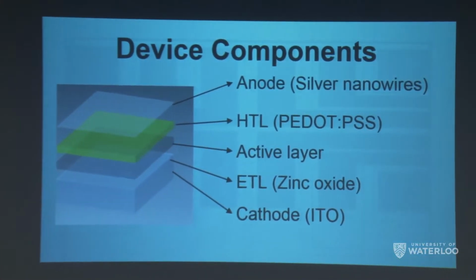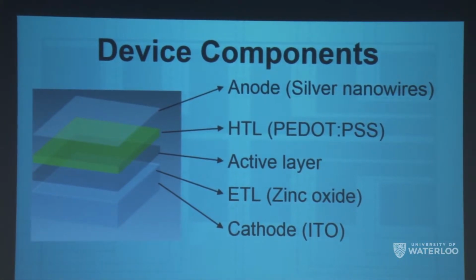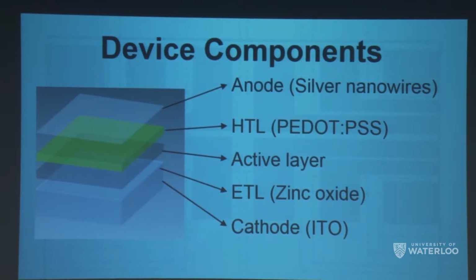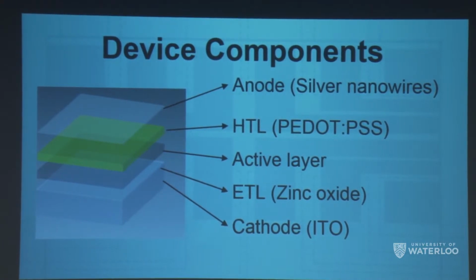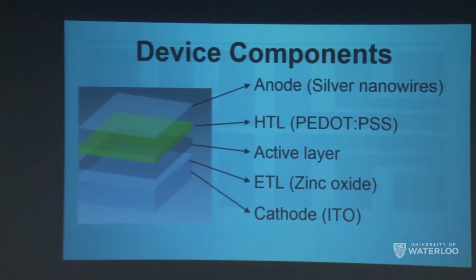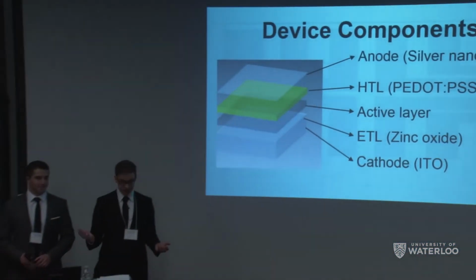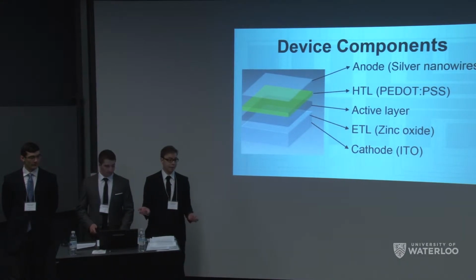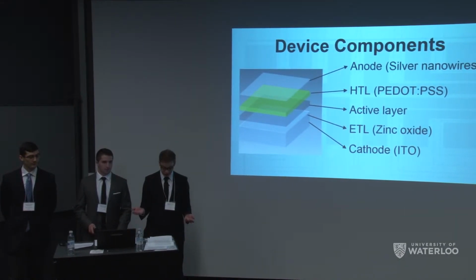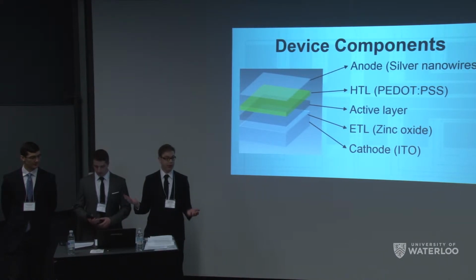We bring in our glass substrate, pre-coated in indium tin oxide. Then we use spin coating to deposit our electron transport layer. On top of this, we can use spin coating to deposit our active layer. From there, we take a second flexible substrate and roll on our silver nanowires. After these have been sintered for better conductivity and adhesion, we spin on our hole transport layer onto the silver nanowires. Then we take our top flexible electrode, and it can be laminated on top of the glass half of our substrate.